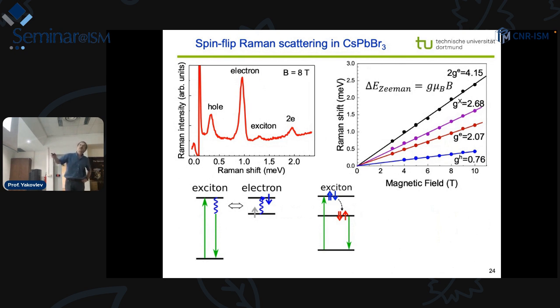How this spin flip Raman scattering spectrum looks for the cesium lead bromide. The whole range here is 2 millielectron volts, so we are very close to the laser line. The magnetic field is 8 Tesla, and we observe very pronounced lines of the hole spin flip, of the electron spin flip, there is an exciton spin flip, and there is also the double electron spin flip. If we change the magnetic field from 0 to 10 Tesla, one can see that these lines shift linearly with the magnetic field, as one expects for the Zeeman splitting, and we can determine these g factors.